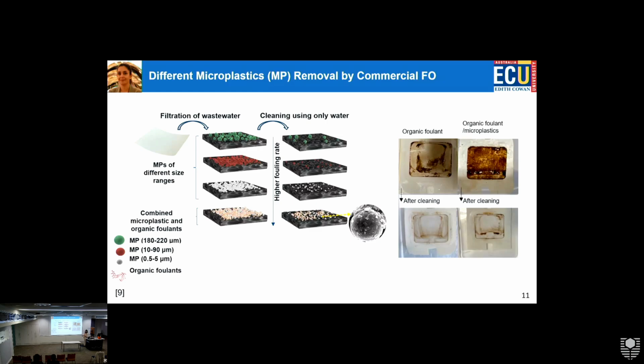And she also tested organic foulants together with the microplastics, as a mixed foulant case, to see the synergistic effects of them with each other. So as you see here, this is one of the microplastics, and these are organic foulants that have attached to it. Same phenomenon is happening for any contaminants that get in touch with microplastics in the environment. And she did organic fouling and organic plus microplastics fouling tests. What you can see here, in the case of organic foulants alone, we have less dark material on the surface, which is basically the foulant accumulation on the surface of the membrane. And in the case of the mixed foulant type, we see that microplastics have increased the accumulation of the contaminants on the surface. This was for forward osmosis, as I mentioned.